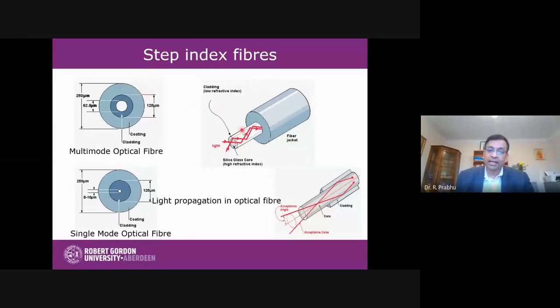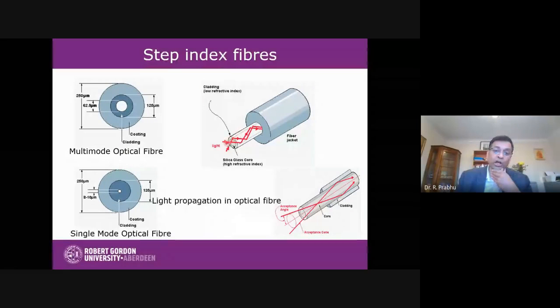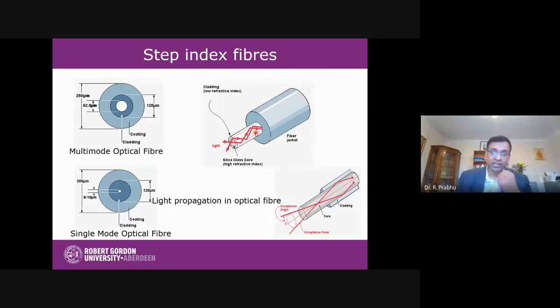So basically, as I said earlier, an optical fiber has a core and a cladding supported outside. In a glass fiber, this is a silica glass core supported by a slightly lower refractive index cladding. This high refractive index core and low refractive index cladding support total internal reflection at this interface. This total internal reflection phenomenon is the core part of the transmission of light through optical fibers, because this is a very low loss, or 100% efficient, reflection. We can transmit light for a long, long distance, probably kilometers and kilometers of length.